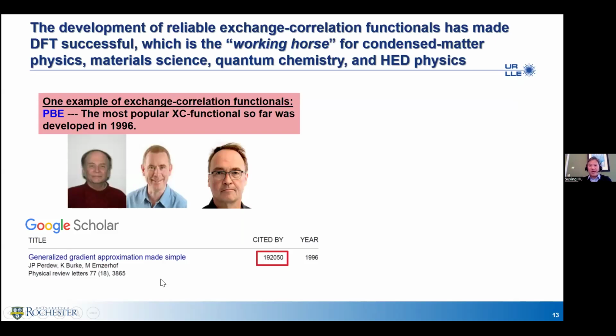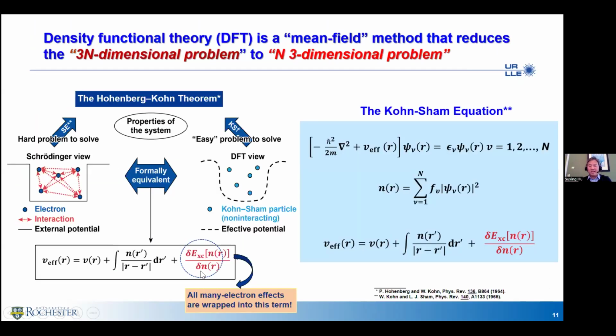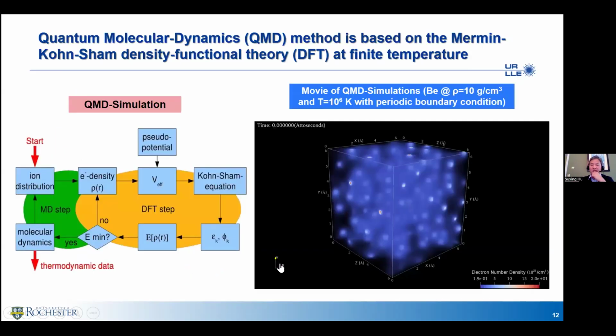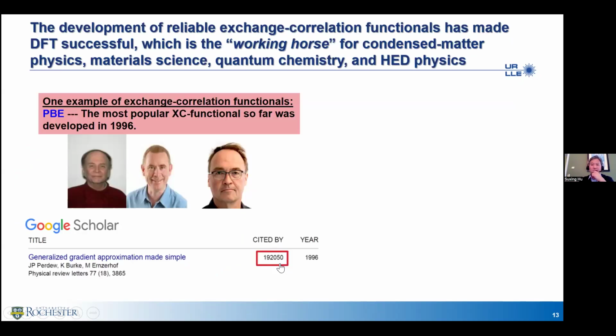Okay, so back to this part, the DFT approximation, the so-called exchange correlation function. For a long time, no one really got what this part should be, until some heroic effort by David Ceperley and co-authors. They used QMC to figure out the exchange correlation function for the electron gas. Based on that, people could come up with the exchange correlation